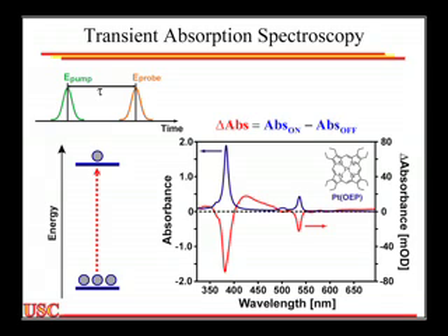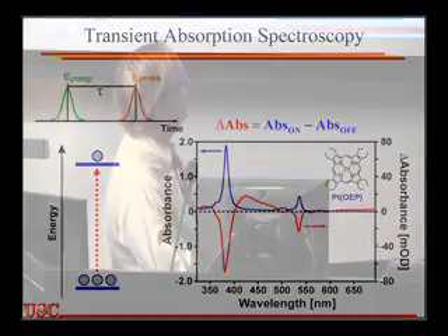And so note that if I take the difference, I've depopulated the ground state, so I'm going to see a negative peak here where I've bleached the ground state. So anything that you see with a negative one is a bleach. That means I've depopulated the ground state. The excited state is going to have a net positive absorption, so I'm going to see a separate absorption spectrum for this molecule in its excited state. But the bigger signals are almost always the bleaches, because these are very intense transitions, but we see both the bleach transitions as well as the growth transitions.